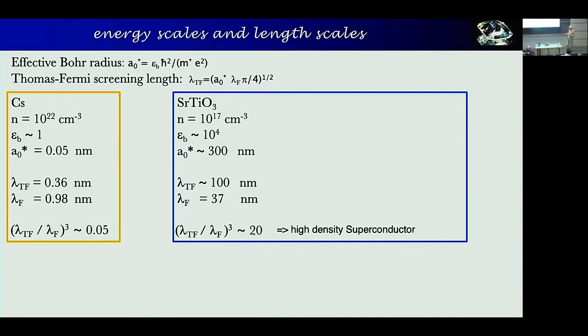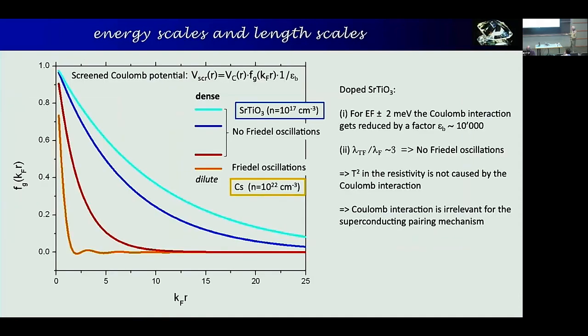Now, why is that relevant? Well, it could be relevant because of what the screened interaction between electrons looks like. This is what it looks like in cesium for these low density systems. But for high density systems, which is what you effectively have, you don't see these oscillations anymore. Or if they appear, it's at some very high value of kF times r, which is really getting irrelevant. So this is really in the regime of more normal Thomas Fermi screening, without any of these oscillations or very weak ones. Another thing that's important is that the entire scale over here is scaled by a factor 1 over epsilon, where epsilon is your background dielectric constant, which was 10,000. And so there is actually no Coulomb interaction, meaning that the Coulomb interaction couldn't possibly play any role at all as electron-electron scattering. So that wouldn't give you a T square. It would also not play a role in any kind of pairing mechanism because it's essentially completely negligible and repulsive everywhere.